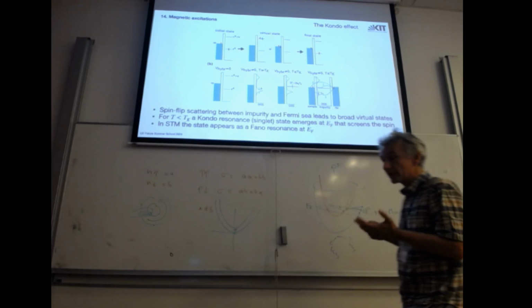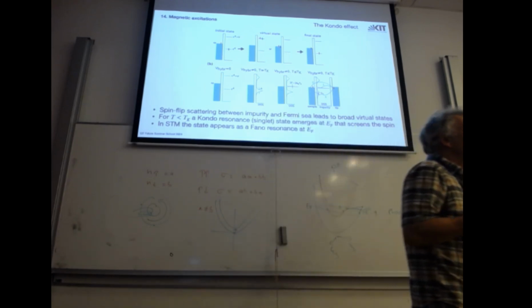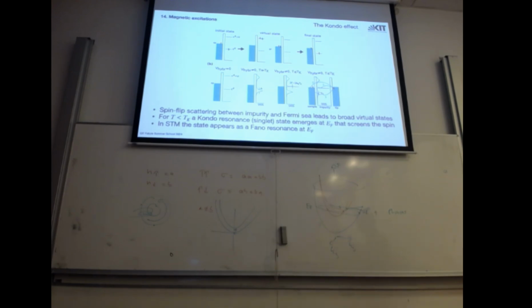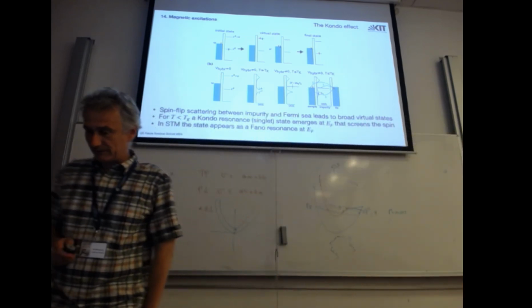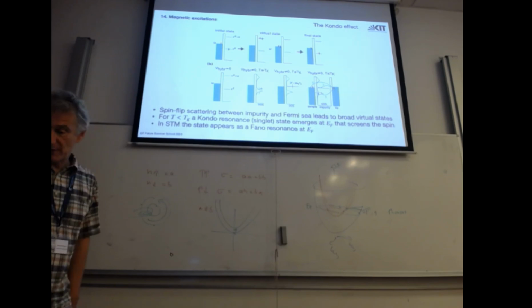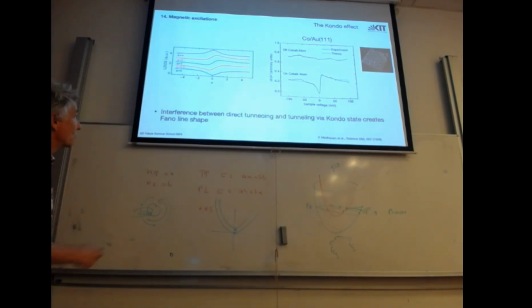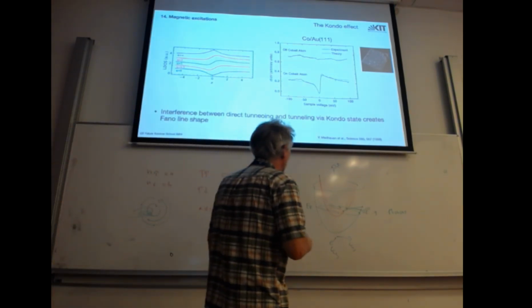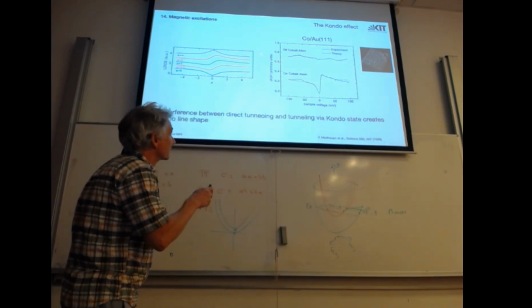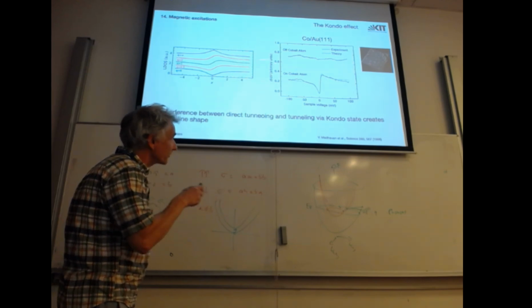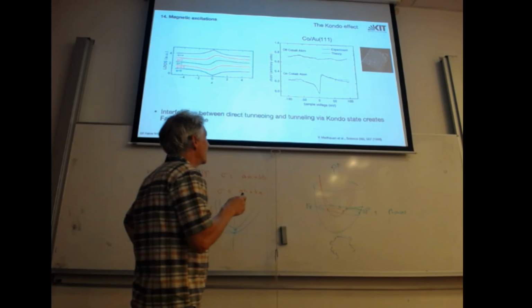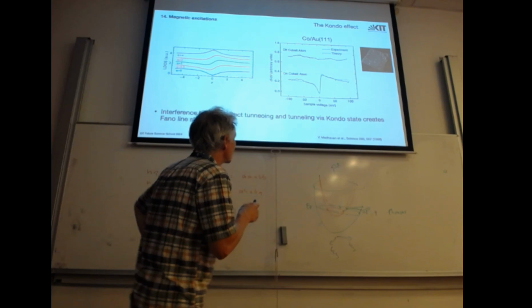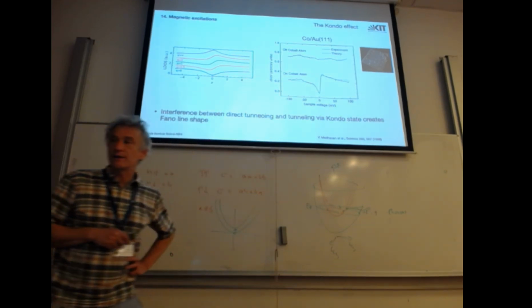It's a two electron state. And what this does is actually screen the localized spin of my localized moment by an oppositely spin polarized electron, and at low enough temperatures, below the Kondo temperature, you have this bound pair singlet. This nicely sits at the Fermi energy, and you can see it with STM. So this is the first example from the microscopy. This is cobalt on gold. This is plain gold surface. You see almost constant density of states, and you move your tip on one of these small cobalt atoms, and then you see this wiggling here.